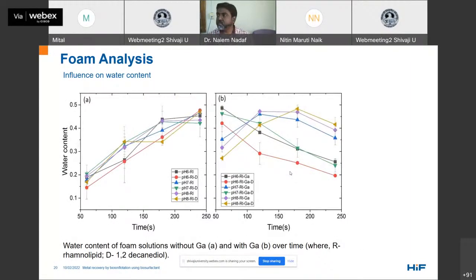As said earlier, water content of the foam matters a lot in the flotation, and we were able to calculate the water content from this foam image analysis. Here we can see that the water content of rhamnolipid foam without gallium, even in absence or presence of decanediol, kept on increasing over time, suggesting that the water drainage from this foam is very less. This might be probably due to free rhamnolipid molecules which are available and they make the foam more stable.